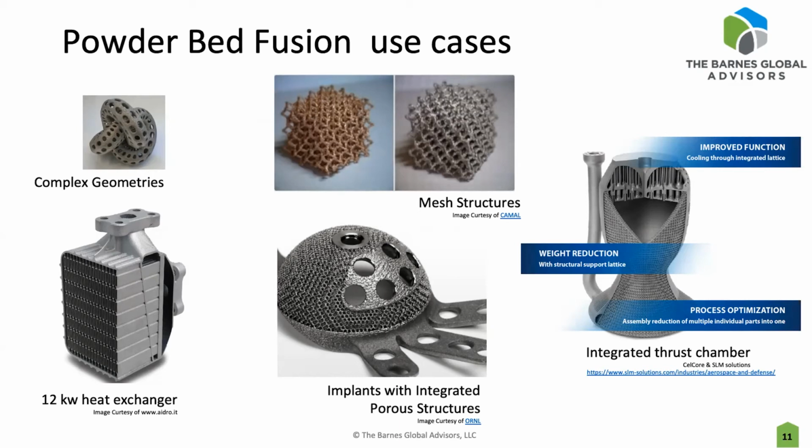The other thing I would like to point out here on this page is the heat exchanger in the bottom left, right? So that's a more or less conventionally designed heat exchanger, right? It's about 1/5 of a conventional, brazed wavy plate, straight plate heat exchanger, and it weighs 85% less mass for the same performance. And so we see this over many different applications that I worked on at a couple previous gigs. The average heat exchanger moved from conventional to additive was 30% less expensive, 30% more efficient, and 30% smaller, in the additive side versus the conventional methods of manufacturing.